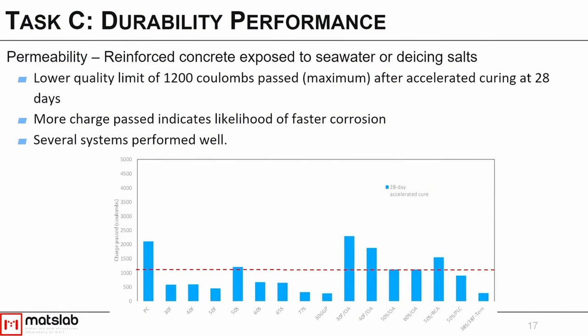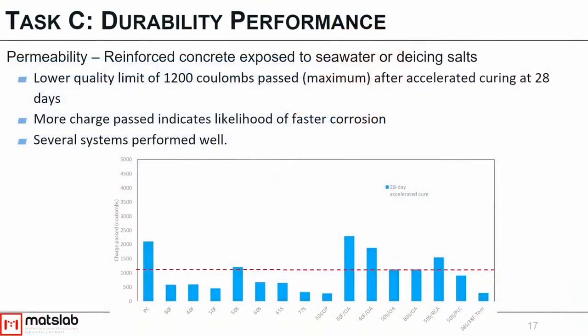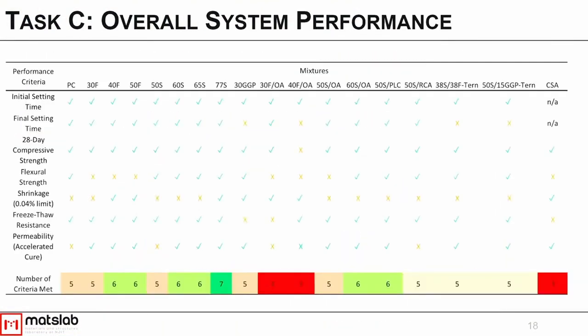This one was not quite as successful with all of our mixtures as some of the other ones, but we still got fairly good performance across the systems. Typically, when you use supplementary cementitious materials, these will densify the system, and so you do expect better performance in the rapid chloride penetration test when you use those materials. So we sort of expected some of these results, but it was good to get a double check on that.